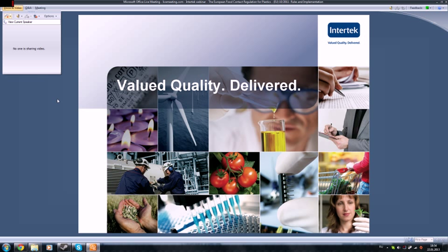Then you can go to a more sophisticated step to use one of those available migration models, which you need to buy, which are costly, and which calculate the migration based on the diffusion through the polymer. And of course, polymer specific and substance specific parameters, temperature and the lipophilicity, are the most important parameters in this modeling. This modeling shows a very realistic scenario of what is happening between the plastic and the food. Of course, it just can give the results with the input parameters you put into the model. So you need to be sure, and you need to know, for example, what is the residual content in the polymer.